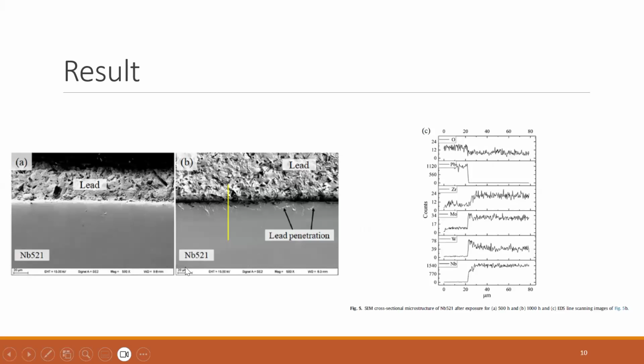So we can see in this figure 5, the cross-sectional corrosion microscopy of niobium alloy. This is for 500 hours, and this is for 1000 hours. You can see the depth of the penetration increased after 1000 hours. And this is the scanning image, and